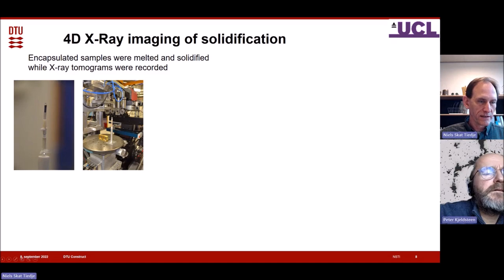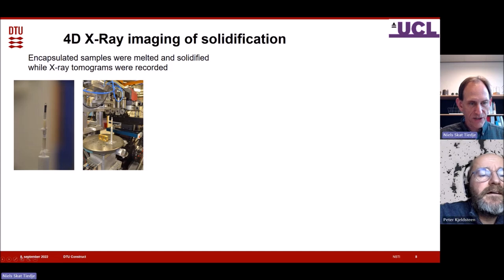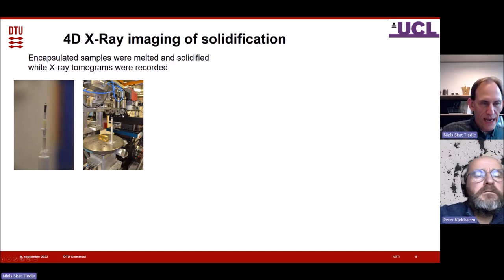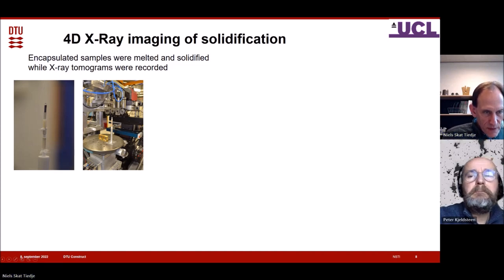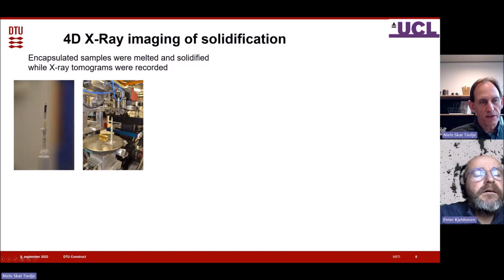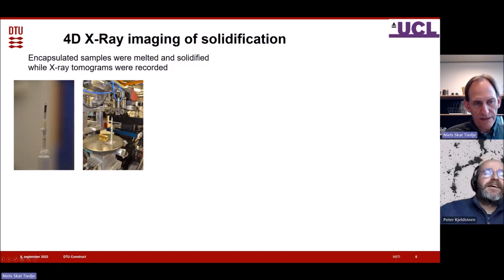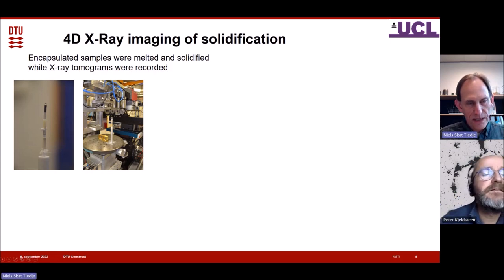It sits on a rotating stage. This is the tip of the sample holder. It sits on this stage, and it can rotate. And do you melt it? Yes. So up here, you can see that square thingy that sits in here is actually a furnace that can be lowered onto this. So this little sample gets to sit inside the furnace. And then we have high intensity X-rays shot through it, so we get X-ray images.